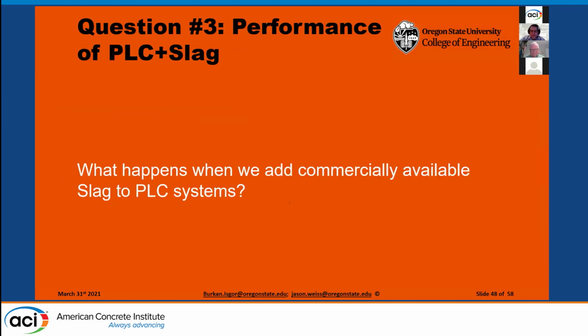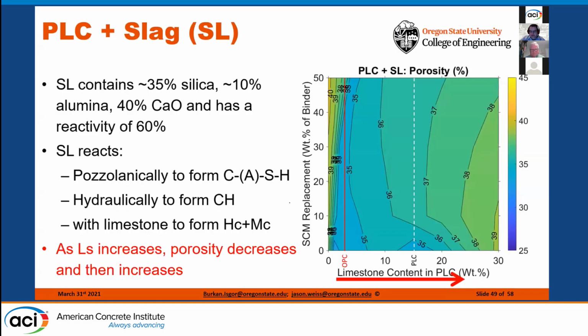So now the question really is, what happens when we add slag and PLC together? And this again is a case where we started to add this into the system because remember, slag is now containing about 35% silica, 10% of alumina, and 40% calcium in the system. Our slags typically measure out to have a reactivity of around 60% using that pozzolanic reactivity test, where we actually account for both the pozzolanic and the hydraulic reactivity.